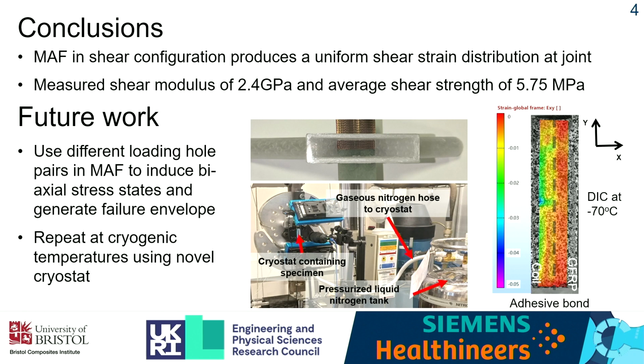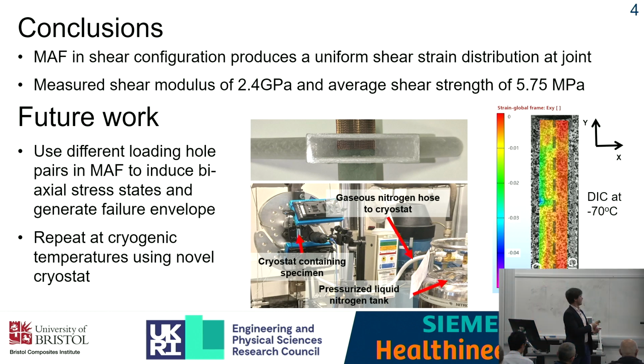So I have devised a novel cryostat which isolates the specimen from the test rig, and so I can apply cryogenic temperatures just to the specimen. And this is using gaseous nitrogen. And on the left is my initial results, and currently I'm just working on getting the noise of the DIC down so I can use the measurement.